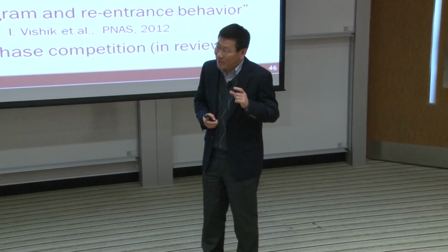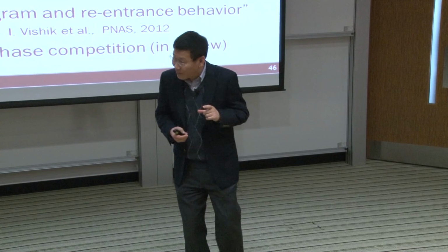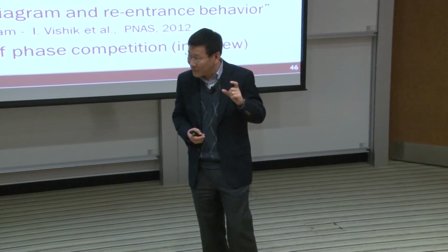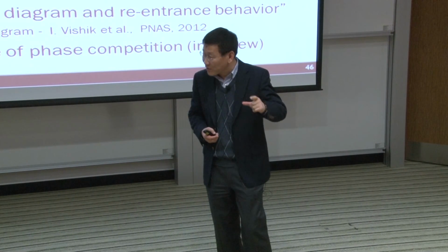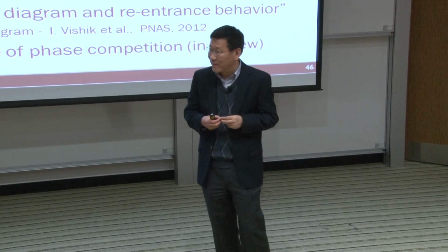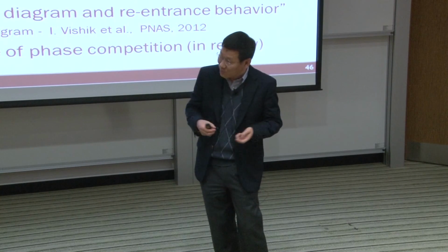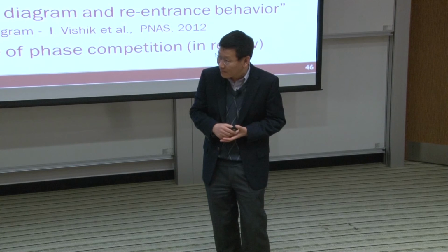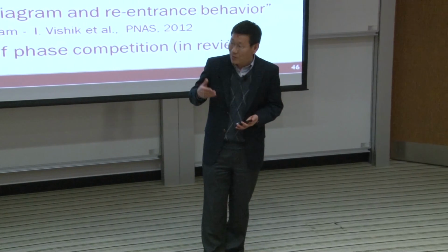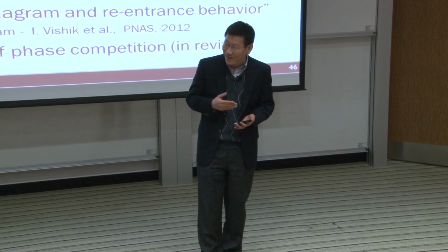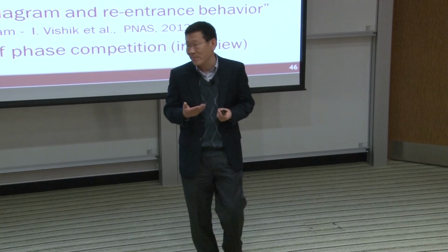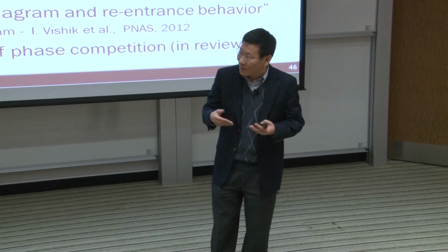From what we have seen on the density wave, we think the periodicity and the Q vector involved is more likely in the charge sector, because the charge sector has a different kind of incommensurate Q vector than the spin sector. Okay, the Q, the magnetic Q. Okay. But as you know, charge density wave and spin density wave are usually coupled in those systems. I mean, but I'm talking about the primary one.